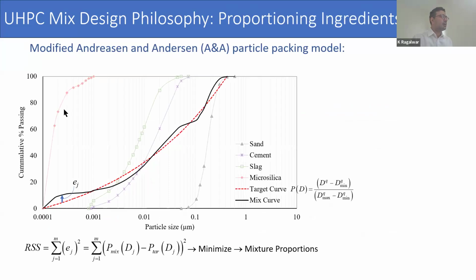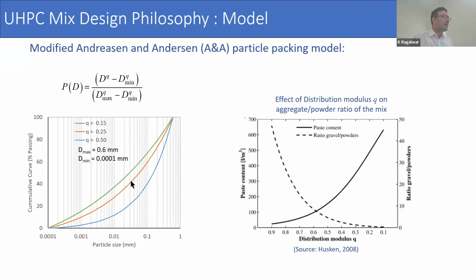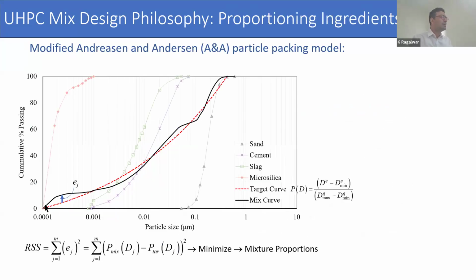So we take into account different particle size distributions such as sand, cement, slag, microsilica, and we set a target curve. The target curve is a smooth curve, which is defined by this equation here. And what we try to do is form a cumulative, which is shown in this black curve. This black curve is the cumulative particle size distribution